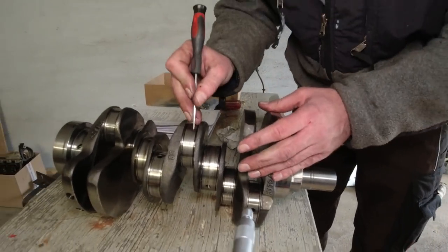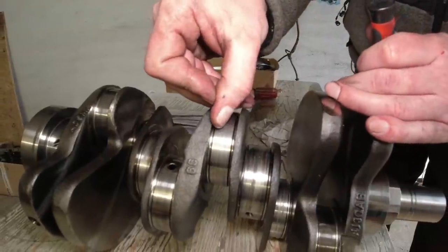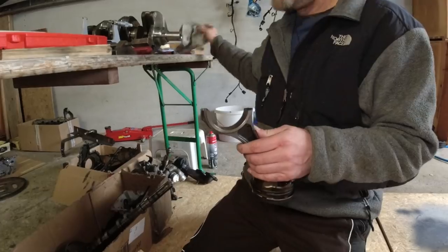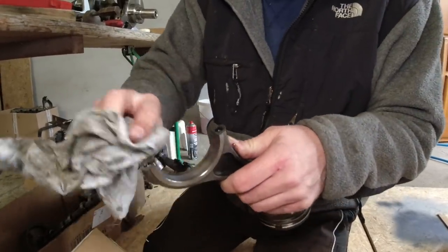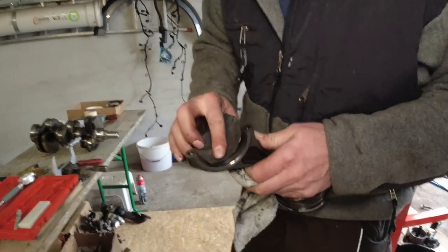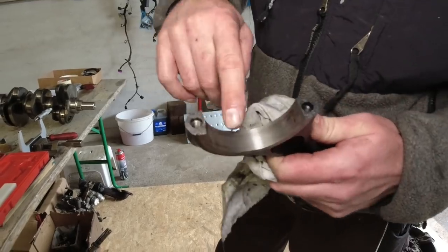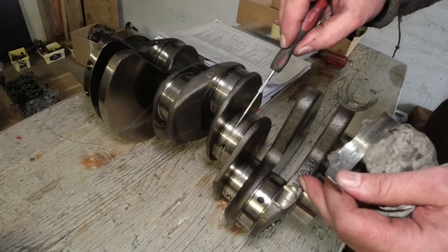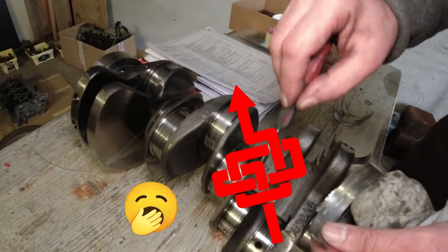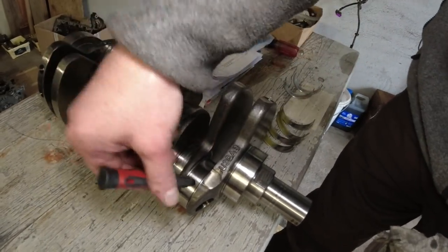The rule of thumb is if you have any kind of grooves inside a crankshaft which make your fingernail get hung up - or if you can even feel it - you need to get the crankshaft reworked. None of them suffered from a slipping bearing inside the connecting rod. I've got here a thousand grit sandpaper and look - when I go over this with the thousand grit sandpaper, it cleans up perfectly. This here supplies this one, and this here supplies this one because of the cross holes. This one gets supplied by this one, which is still fine.